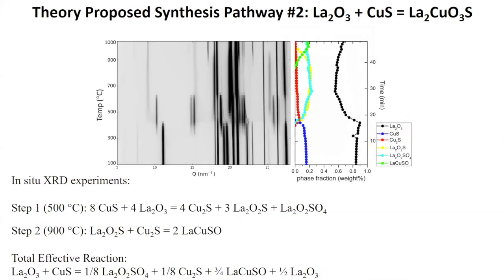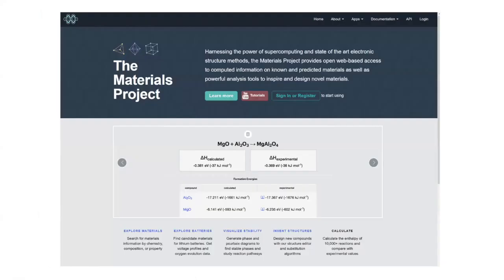All right, something similar happens when we take another route, which is lanthanum oxide plus copper sulfide. This is another synthesis pathway that we could consider. And the upshot is that, again, we have copper sulfide, and that is reduced to copper 2 sulfide in the first step. And then the final product in this case is a cleaner synthesis of lanthanum copper sulfur oxygen. So again, that didn't work out. But I want to stress that we found all that out over the course of maybe a day or so at the synchrotron, as opposed to spending months trying to make that work.